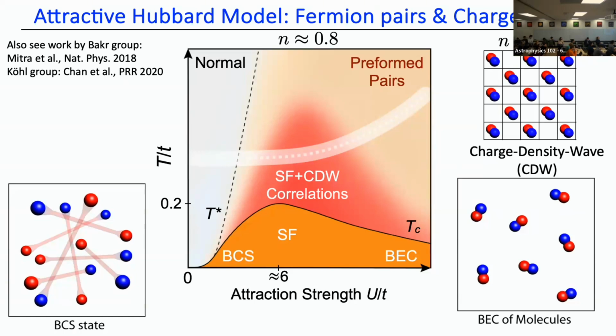There is one more ingredient other than what we know from the bulk, and that's another way that the system can be very, very happy in the lattice, and that's a charge density wave. You can have the pairs, yes, but they can also organize not in the superfluid state, but in a crystal, the charge density wave. Doublon, hole, doublon, hole. And at half filling, it is as good a state as the superfluid state. And in fact, the order parameter therefore has 3 components: x, y corresponding to the superfluid order, and z corresponding to charge density wave order.